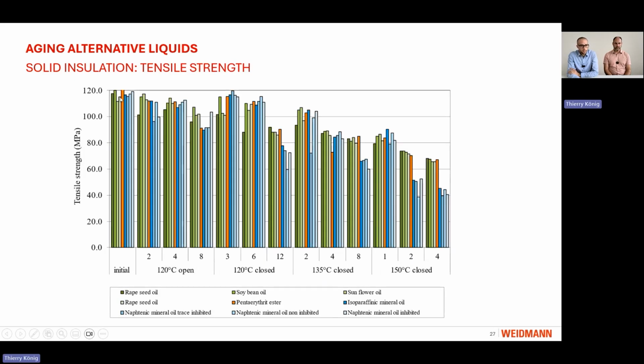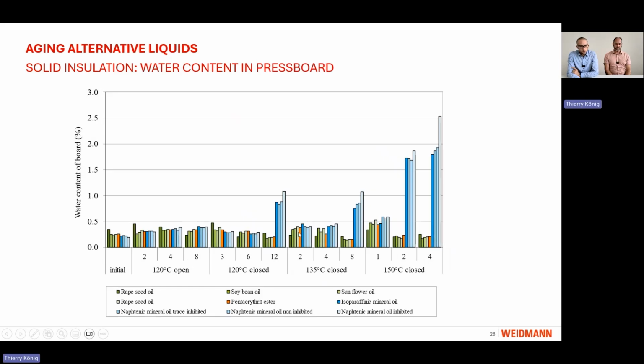As Lars already mentioned, the tensile strength can be correlated to the degree of polymerization. So this effect of higher deterioration of the pressboard aged in the closed system, we can see here, has a faster decrease, caused by the higher water content in the mineral oil. For the water content in the pressboard itself, in the open system there can hardly be seen any effect, but in the closed system, the water cannot disappear. So we see an increase of the water content in the pressboard in this closed system, and also in the 135 and 150 degree systems. Only the water content in the pressboard is increased which is aged in mineral oil.